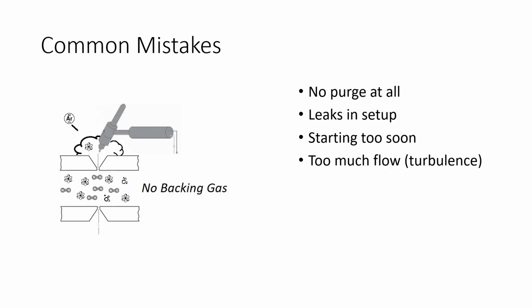Too much flow. We put way too much gas in there. We're going to get a lot of turbulence, and it's going to flow and just look nasty. We're going to get contamination. If we have too much flow, it's going to pull oxygen and nitrogen in there, and it's going to contaminate our weld puddle. Well, the back side of it, that root side of the weld puddle, we're going to get sugaring.